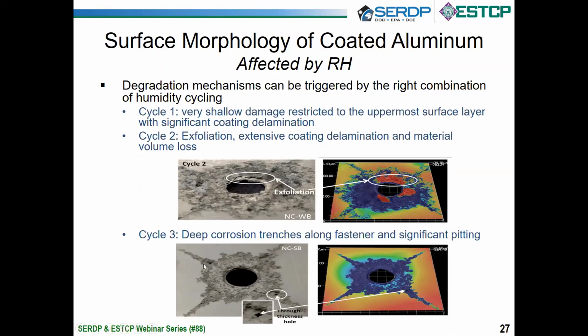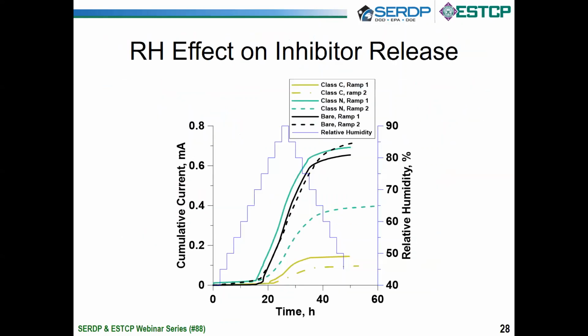In the third cycle, where we fully dried the sample, we again see fairly significant coating delamination, but we see very deep attack. In fact, this is a pit that, if you hold this up to the light, you see light coming through the sample. So the kind of attack where you see this exfoliation happens in these semi-drying conditions, but also the degree of attack that you see is a function of the total time of wetness in a given cycle. Again, these two samples saw the exact same total time of wetness, and how we did that across the cycles was important.